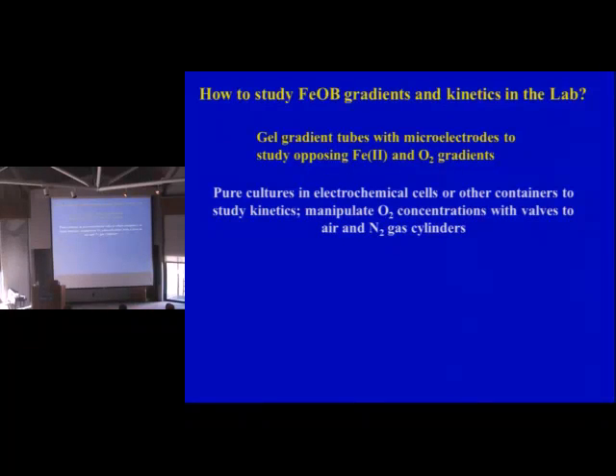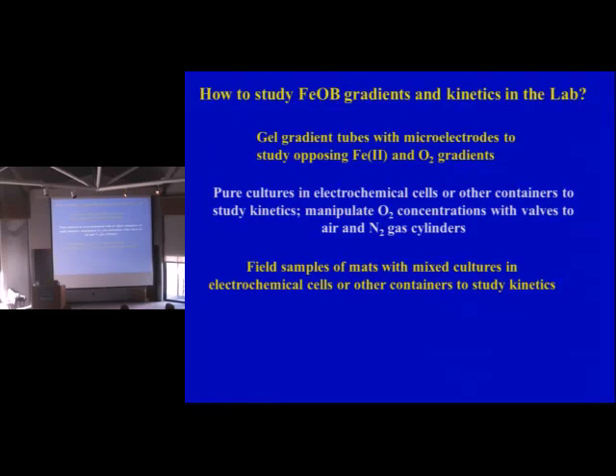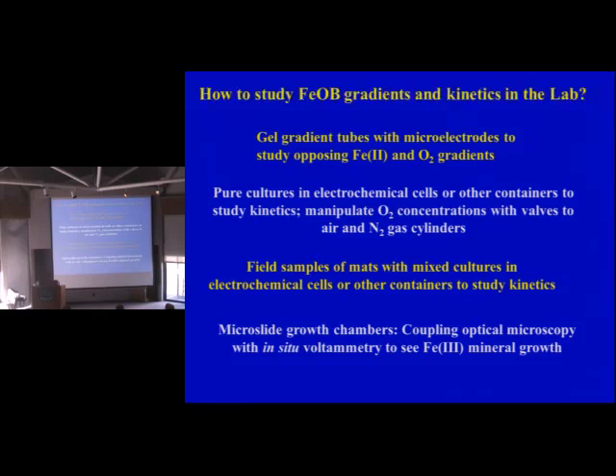We have electrochemical cells. We can put the cell in culture. And we can actually manipulate the oxygen concentration to some low value. It could be like 10 micromolar, for example, to higher values. We can actually go lower than that. We've actually done some work. We've taken field samples and thrown them in little vials and done the experiments. So I'll show you these experiments. And then we're going to show you the latest stuff we're doing, which we're ready to submit.